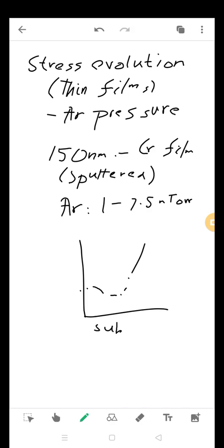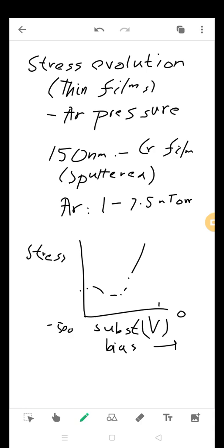So it is based upon the substrate bias in volts that we provide, and it has varied from, say, minus 500 volts to 0, and the stress, which is expressed in gigapascal, was found to vary up to 2.5 gigapascal. Negative means compressive stress, so it has crossed the 0 mark and it has become tensile.